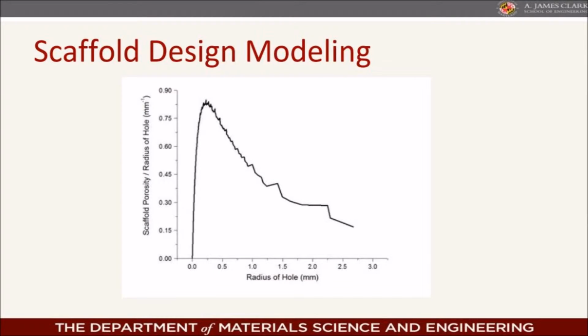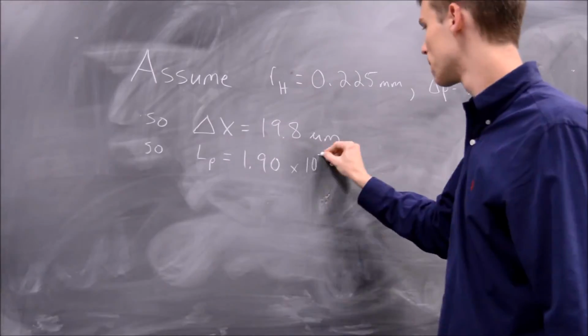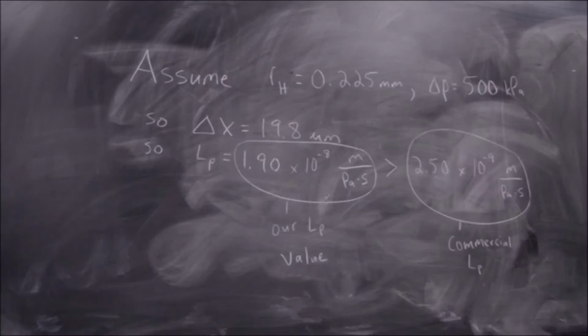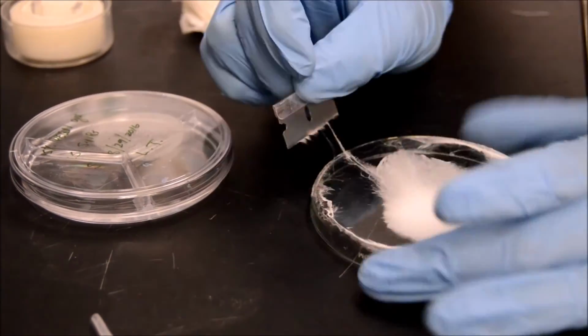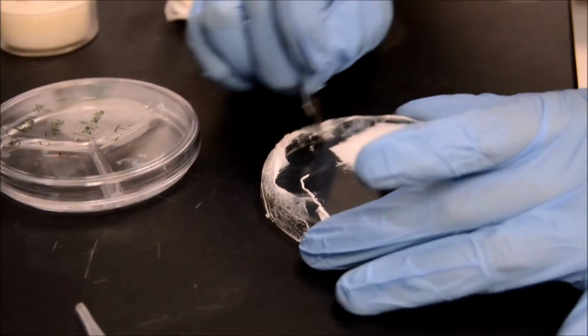We plotted this metric over a range of hole sizes, assuming that any scaffold would require at least 0.5 millimeters between holes due to processing constraints. This metric had a clear maximum when the radius of the holes in the scaffold was 0.255 millimeters. Once the hole size of the scaffold was determined, the thickness required to provide sufficient strength could be calculated. Our model predicts that a 20 micron thick nanofibrous mat should allow us to operate at the desired pressures and would offer exceptional performance. After the design phase, we began the prototyping process for our filter.